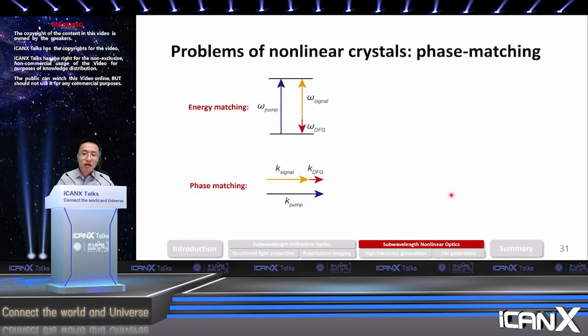But there are a couple of problems with conventional nonlinear crystals. The first one, as I mentioned in the beginning, is phase matching. To get very efficient frequency conversion, other than satisfying the energy matching condition, you also need to satisfy the phase matching condition. For efficient terahertz generation, the nonlinear crystal needs to have identical refractive index in the near IR and in the terahertz.